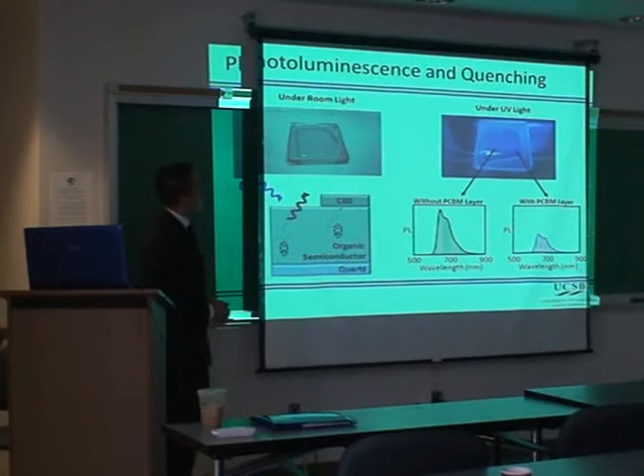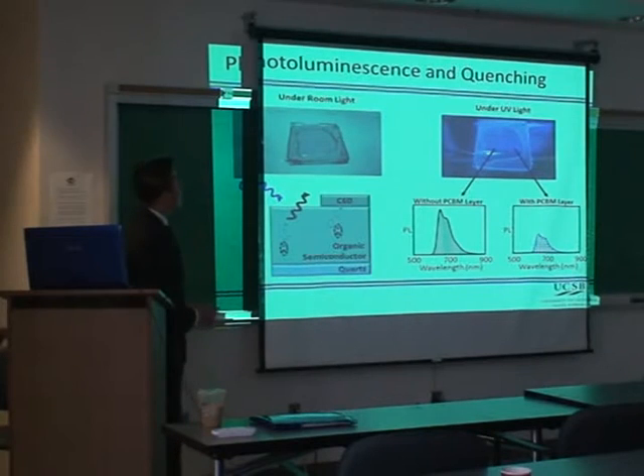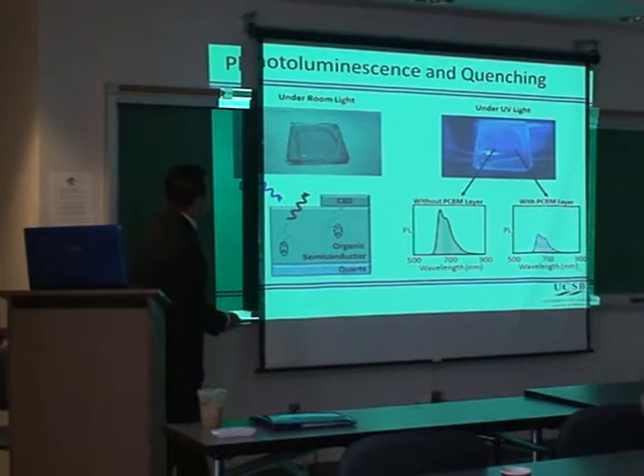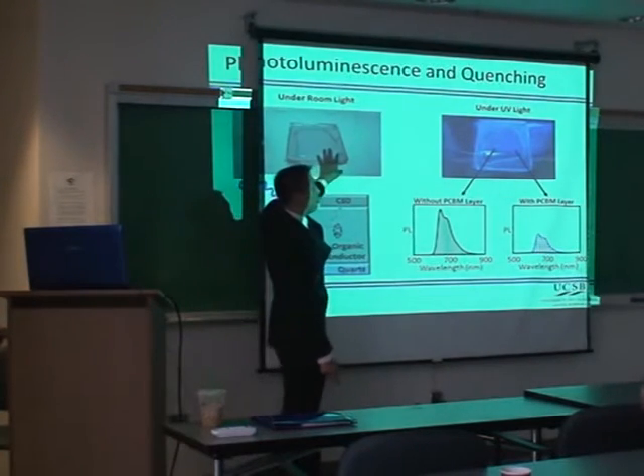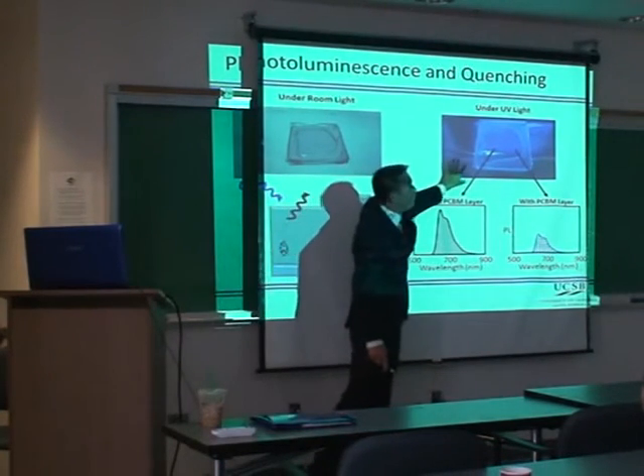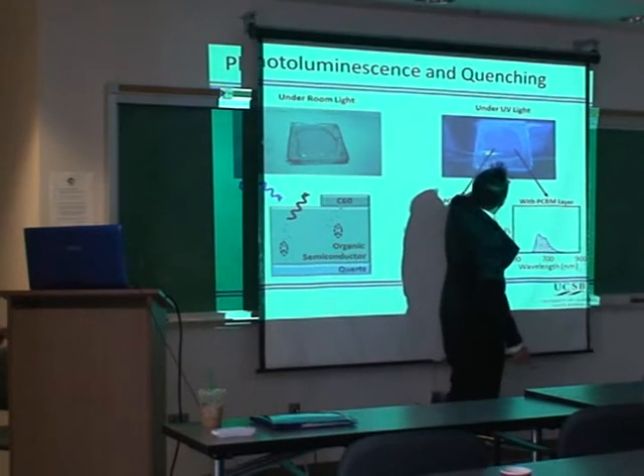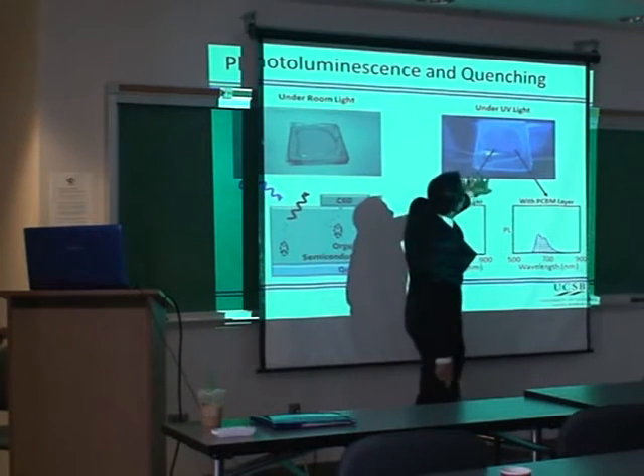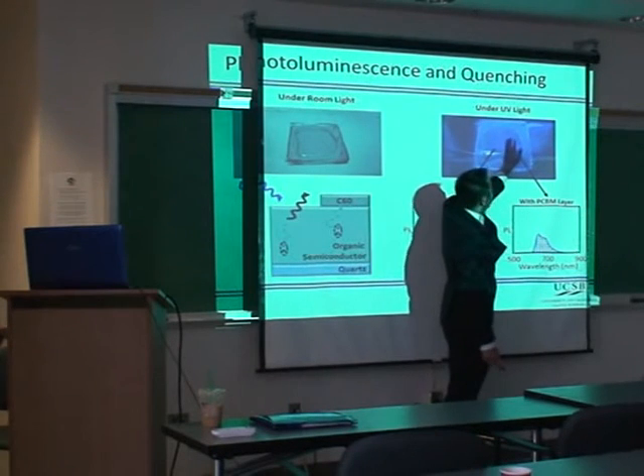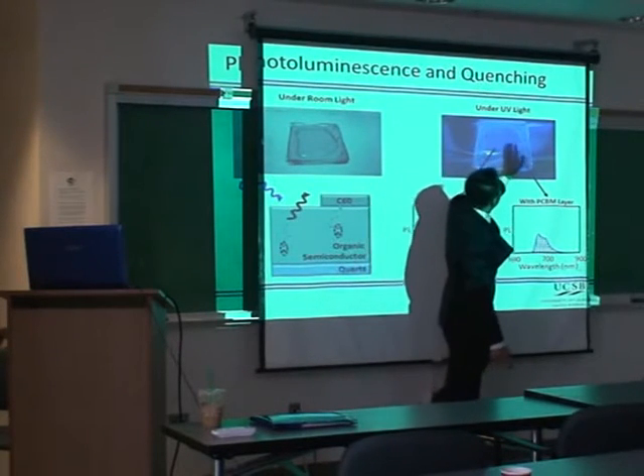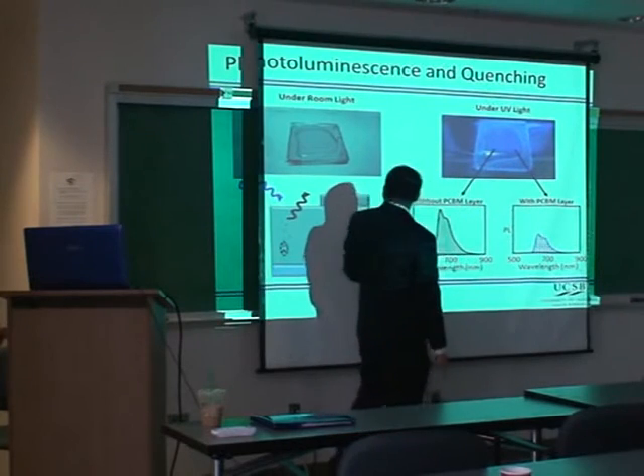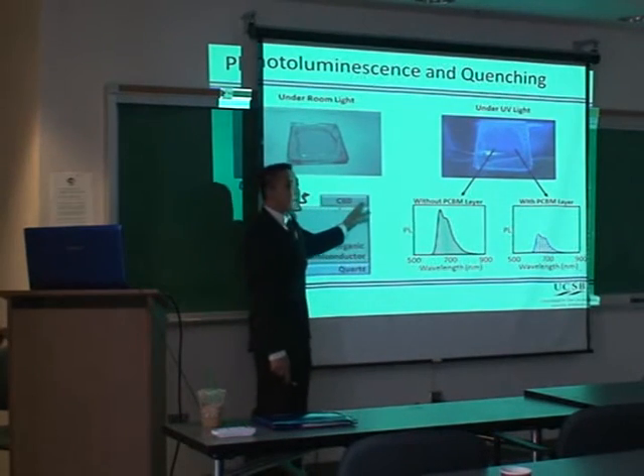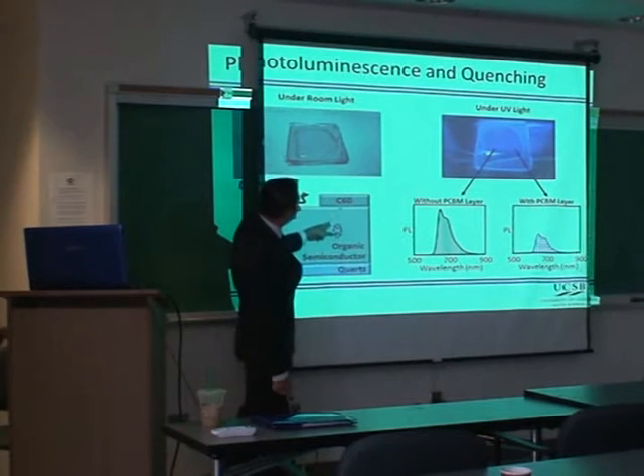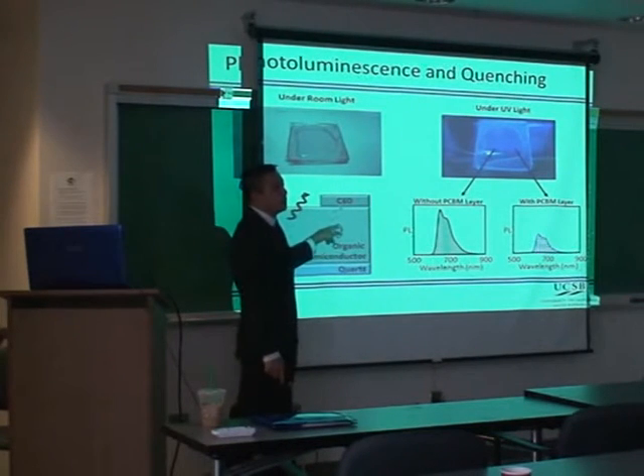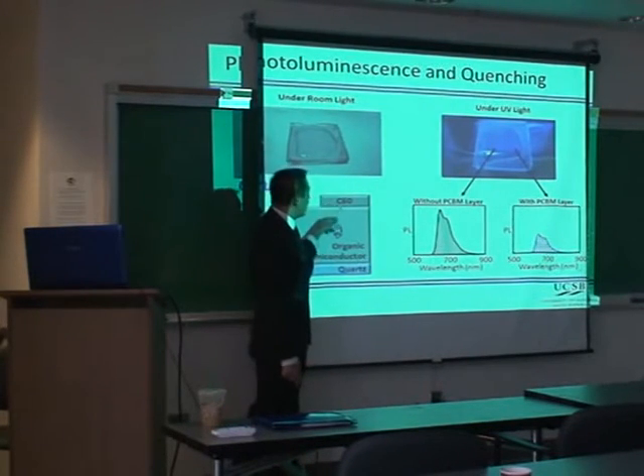So I wanted to take a step back and talk about what's actually happening in these films. What happens when we excite them with light. So you see here, this is the regular film under room light, but if we put them under UV light, you begin to see this fluorescence. And it's kind of hard to see because the color contrast is weird, but the right side is actually dimmer than the left side. And the reason why the right side is dimmer is because the right side has this layer of C60. And what this does is that when excitons are generated near this C60 layer, there's a good possibility that they will reach this quenching interface and be quenched.